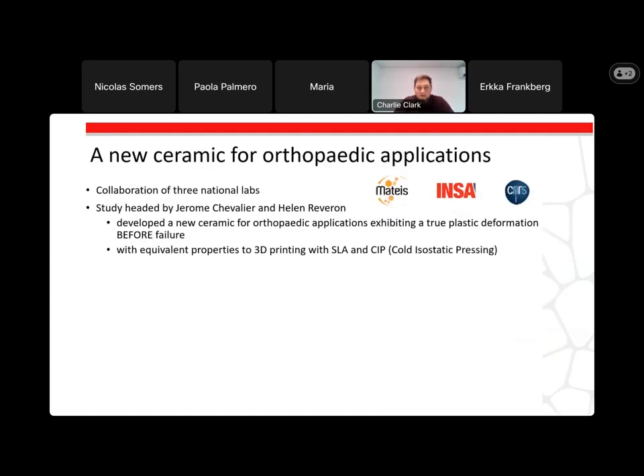So it was a collaboration of 3 national laboratories, where the study was headed by Jerome Chevalier and Helen Reveron, where they were developing a new ceramic for orthopedic applications that exhibited plastic deformation before failure. And the idea as well was to obtain equivalent properties with the 3D printing of SLA as you would with conventional methods such as cold isostatic pressing. So the laboratory itself was coming up with this cerium stabilized zirconia powder, and our part in the collaboration was to come up with a way to 3D print it, and so offer tailor-made products like we did with the HAP skull implants.